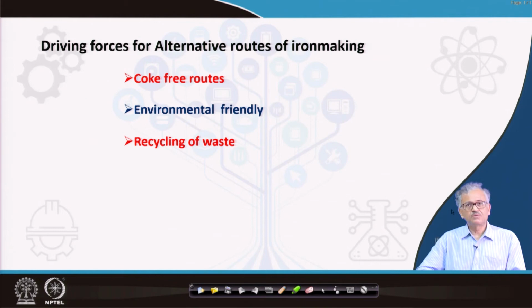You know that we cannot use it in the blast furnace, because the blast furnace is a very complicated chemical reactor. It is, as I repeatedly tell, thermally and chemically a highly efficient reactor, but to maintain its good efficiency it requires very good quality of burden. Burden quality has to be very good in the blast furnace because of its complexity, because you have a dry zone, and then a wet zone in the bottom of the blast furnace, and then it is demarcated by a cohesive zone, and they interact in such a nice way.